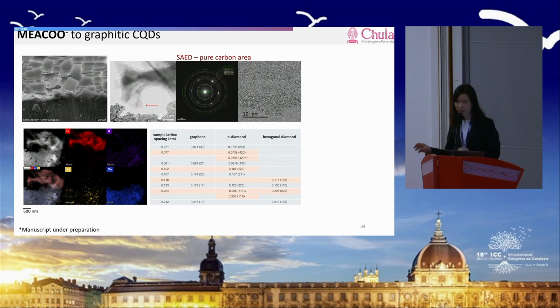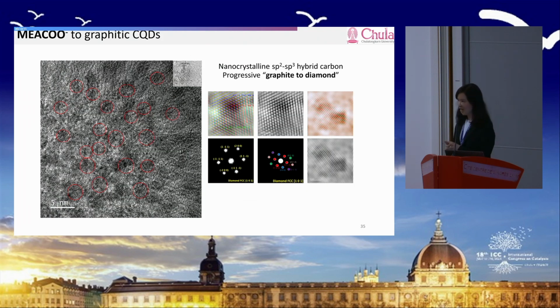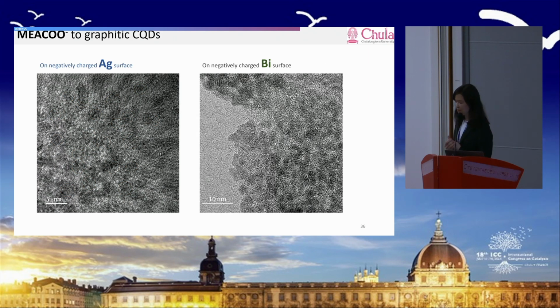And we take a closer look at these carbon films on the electrodes. We just take the carbon out and do diffraction at the pure carbon area. They show very nice crystalline structure that matches perfectly with graphene. And there's also some lattice spacing that matches with progressive diamond. So the carbon products on the electrodes have sp2, sp3 hybrid carbon, but they are very well crystalline in nature. It's been called something like progressive graphite to diamond. We really make diamond here.